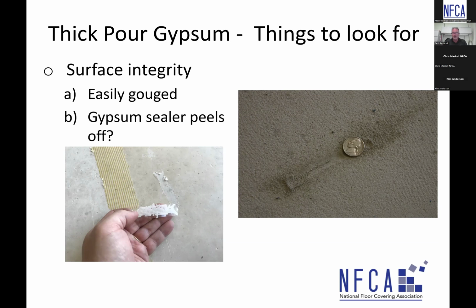I've seen a lot of weak material that did not have to be weak. It was an installation related situation. And I can tell you that the gypsum that is manufactured is an engineered material, and with the right amount of water and the right amount of sand, it can achieve the published strength values of that product. But too often we see, not on an everyday basis, but we do see things get overwatered on site, or too much sand, things like that.